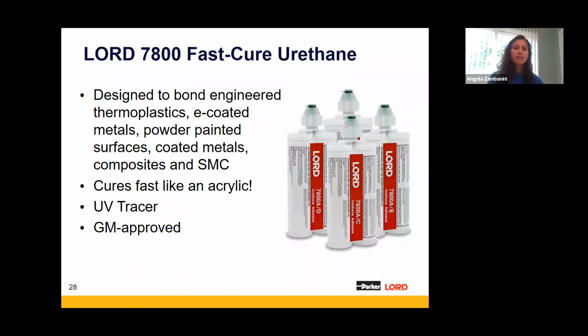The 7800 is a urethane adhesive designed to bond plastics, E-coat, powder coat, all kinds of different surfaces, coated metals, composites, SMC, and it cures really, really quickly. The great thing that caught on with acrylic adhesives is they have decent open time, but their handling time is so quick. You can reach 1,000 PSI in minutes. The great thing about this new 7800 urethane adhesive is that it behaves just like an acrylic. So in less than an hour, you'll have 1,000 pounds per square inch of tensile strength, which means that you can really move quickly when you use this product.